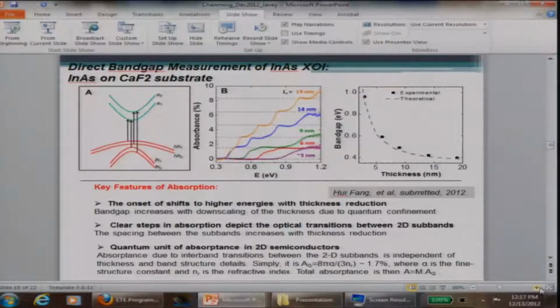And that's what we have done here. And here you're looking at the absorption spectra of indium arsenide with different thicknesses, starting from 3 nanometer all the way up to 19 nanometer as a function of photon energy. The onset of absorption, of course, is your band gap or your effective band gap.